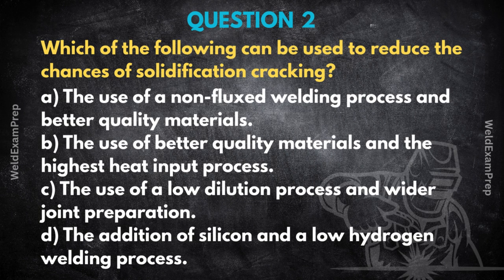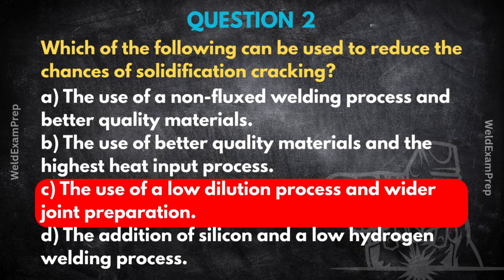Okay, for reducing solidification cracking in this context, the best approach listed is C, a low dilution process and wider joint preparation. Low dilution and wider prep. Let's break that down. What exactly is solidification cracking? It's often called hot cracking. It happens right as the weld metal is solidifying.